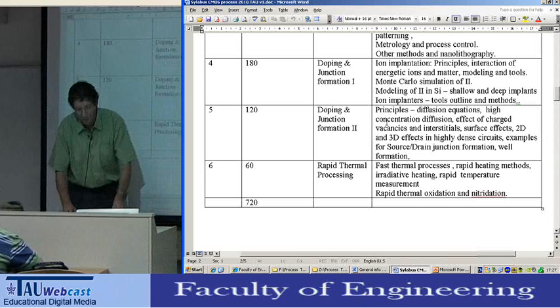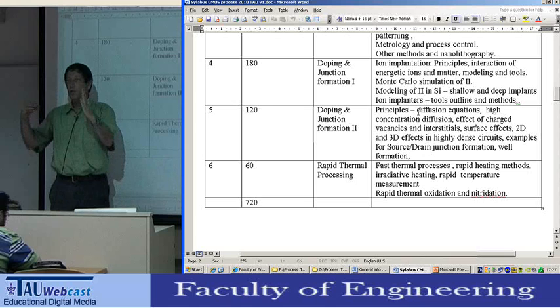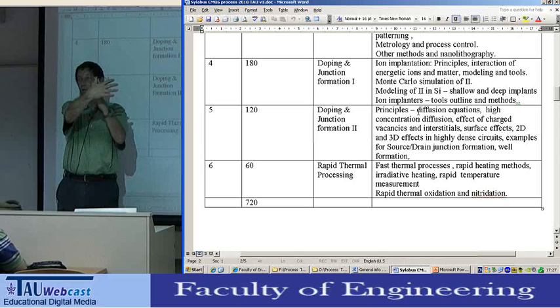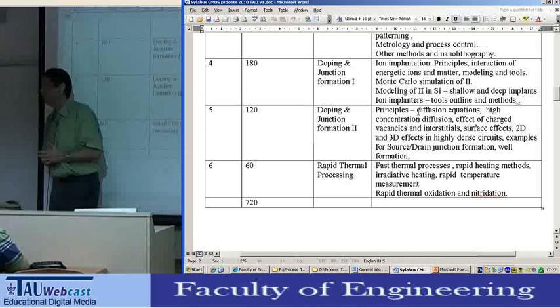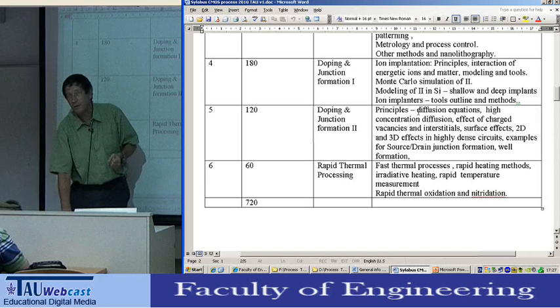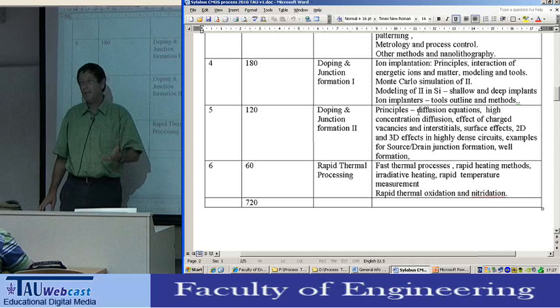Once we know to do ion implantation, the ions penetrate the silicon, we heat the silicon, and the ions diffuse. And once the ions diffuse, we have to solve the diffusion equation. I'm going to show you what equation to use. And there are many, many non-linear effects. And the biggest problem in modeling junction is that the diffusion is not linear.